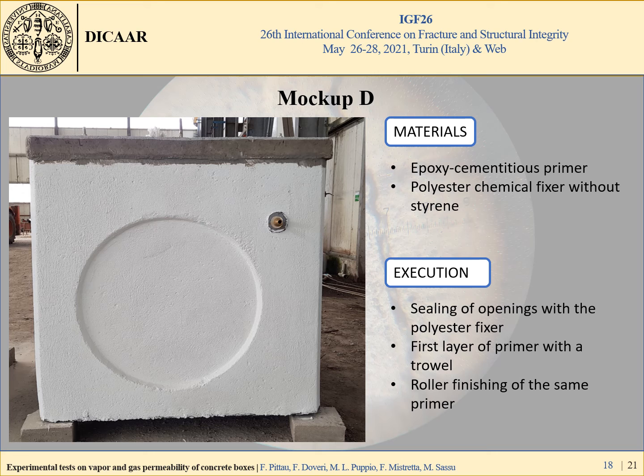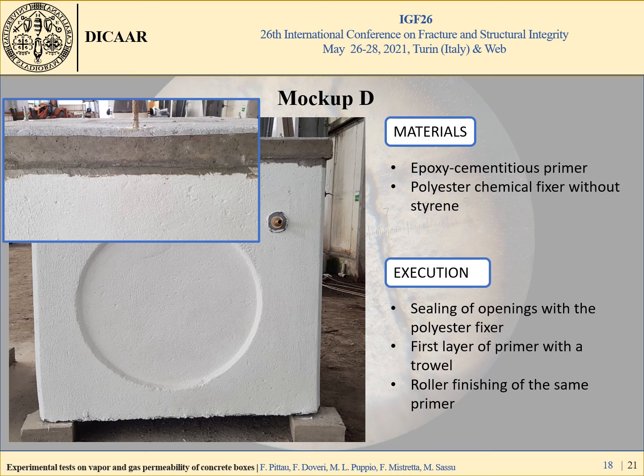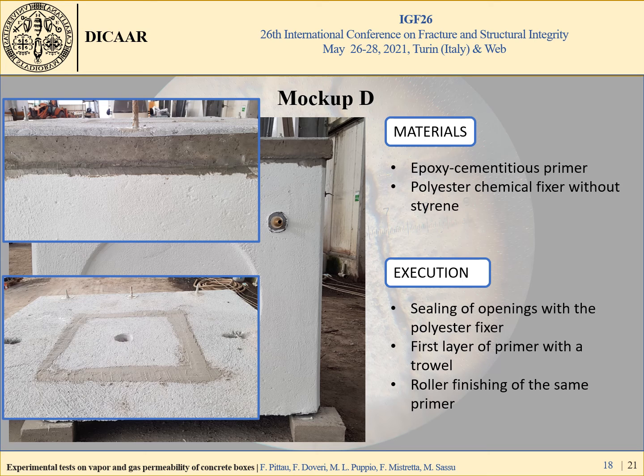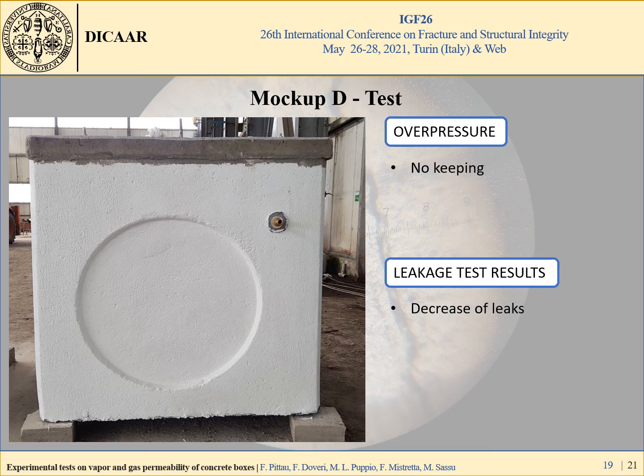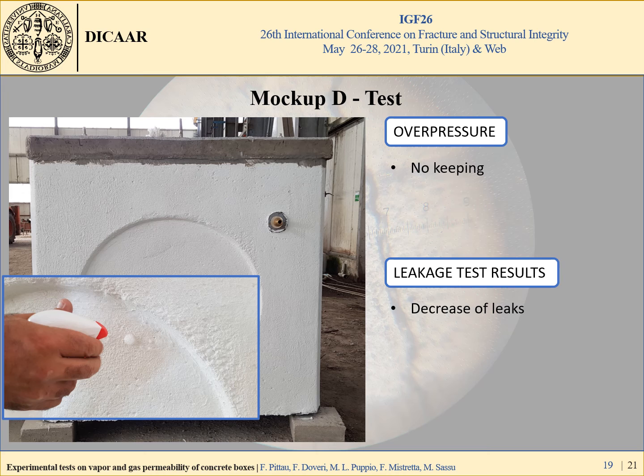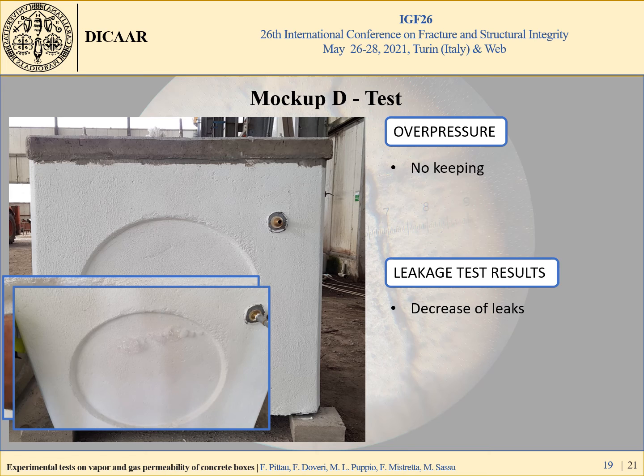The last mock-up, D. Also in this case, the processing was executed by a skilled worker. Here, two materials, one for the discontinuity and one for the walls. The fixer used to seal the discontinuity is applied with an application gun, and the primer is applied with a trowel, but it can be applied with a normal plaster pump. Also in this case the behavior of the test was not good, like mock-up B. No overpressure is maintained, and the leaks decrease, but not as much as we expect. The polyester fixer was a good choice to seal the discontinuity. No leaks were identified.